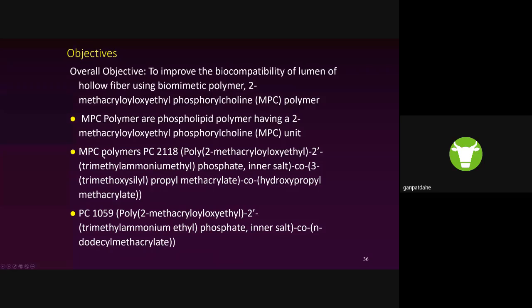We sourced these polymers commercially, and they are PC2118 and PC1059, which are the numbers the supplier has given to those polymers. We use the same setup, but in the bore solution we dissolve these polymers in ethanol, because this polymer is not soluble in water. The ethanol is the solvent for this MPC polymer, and ethanol can also be a good coagulant for making hollow fiber.